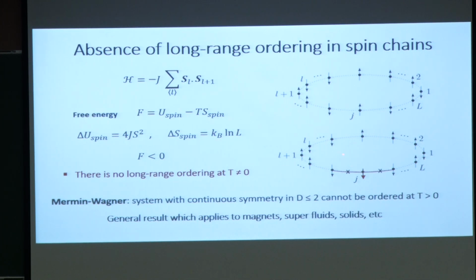Do you see that? Because you can flip the spin at any one of these sites, whereas your U is a fixed number, because you have only made two bonds unhappy independent of where you flip the spin. So you can flip it anywhere. So for a long enough chain, this entropy term will win over this U, and therefore your free energy will be less than 0, and hence a no long range ordering situation will be more preferred compared to a long range ordered state.